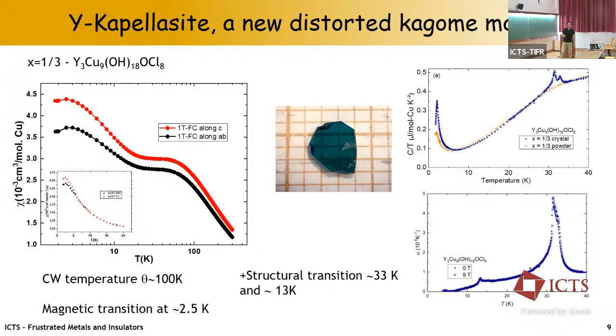And besides, if you look at the thermal expansion, there is... they are not there. If it would be possible to just move the black box there. Okay, I'll tell you what you should see behind. In the thermal expansion, there is a signature as you see in the heat capacity, but there is also a small peak that is behind there at about 13 Kelvin. And that has no counterpart in the heat capacity and neither in the susceptibility.